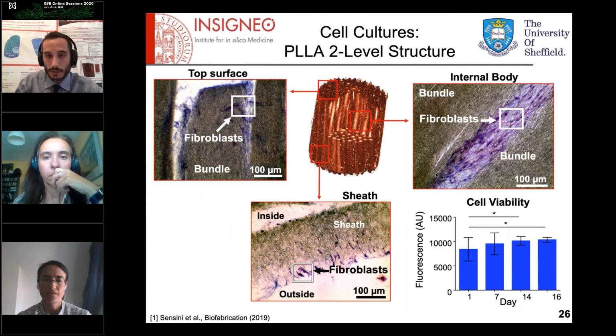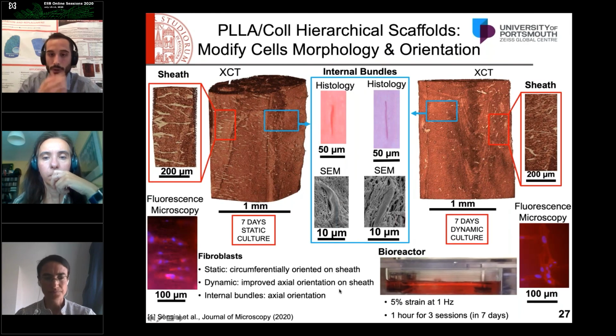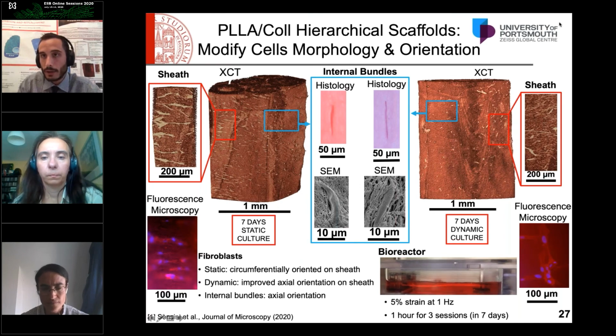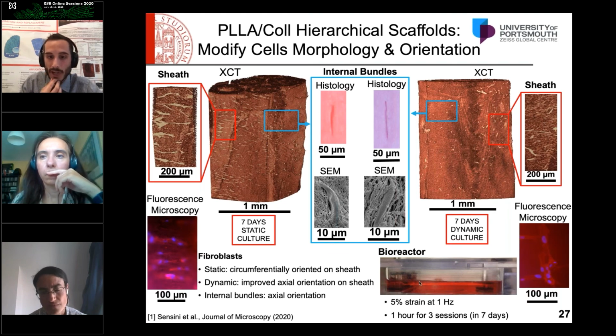Basically the most relevant study we did about cyclic testing in a bioreactor is this one. We tested the scaffold for one week inside a bioreactor, and what we saw is that the scaffold was able to resist without any problems inside the bioreactor and cell culture medium during the cyclic tests.